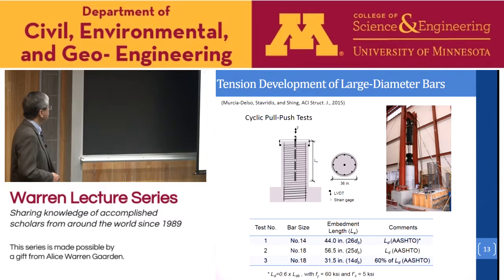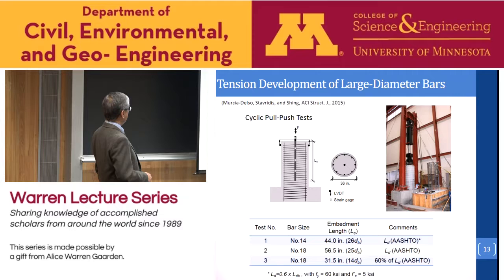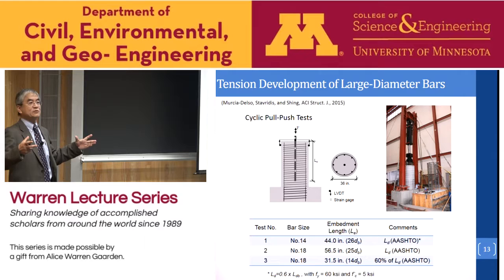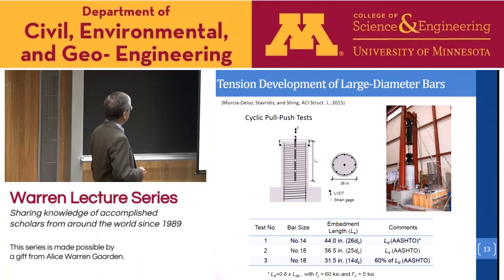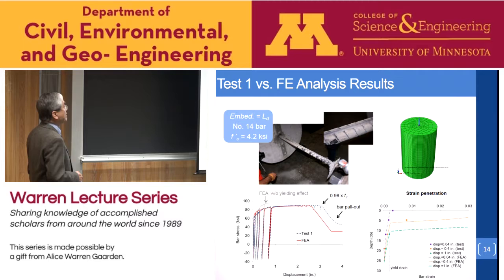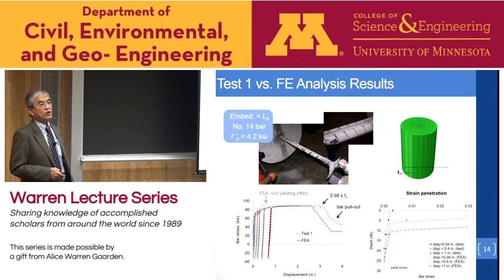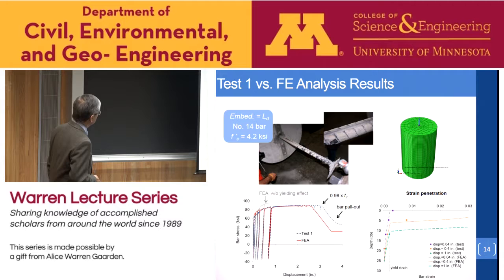Okay, and this development length is based on the basic development length provided by AASHTO times the 0.6 factor, which accounted for the situation that is well confined. So I'll just show you one test. It was the first test on the number 14 bars, okay? And actually, the concrete strength in that specimen did not reach our target strength of 5 KSI. It only reached 4.2. So somehow the concrete was weaker for some reason.